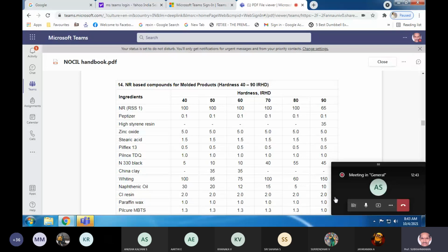The 6PPD anti-ozonant and the antioxidant, in combination, give protective cover to a hydrocarbon rubber like NR. Why NR? Because we look at the cross-linking for every 100 to 400 monomer units.